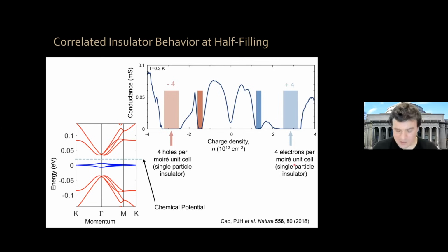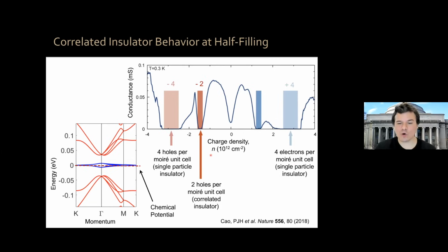The interesting thing happens now, if you add 2 holes per Moiré unit cell, your chemical potential, your Fermi energy, is now in the middle of a band, of the valence band. The system should be an extremely good metal, okay? And on the other hand, the system is an insulator. The same thing happens if you put 2 electrons per Moiré unit cell. The system should be a very good metal. Instead, it is an insulator. These insulator states that happen when the Fermi energy is in the middle of a band are correlated insulator states, okay? Due to Coulomb interactions between your electrons.